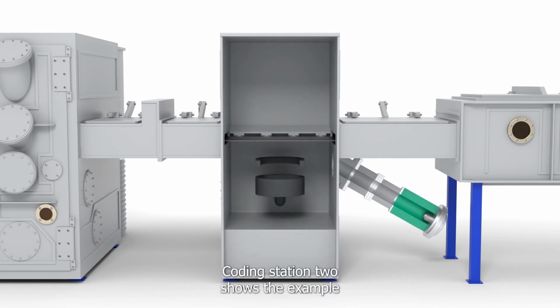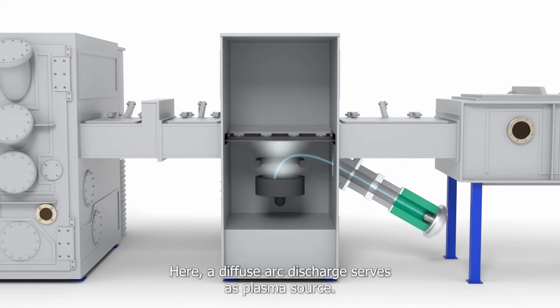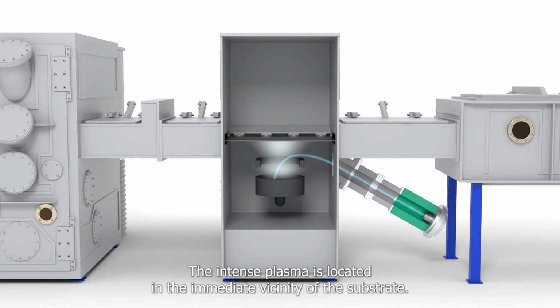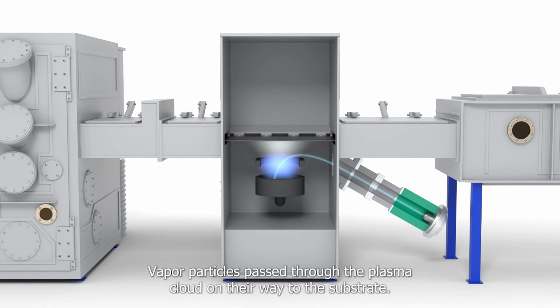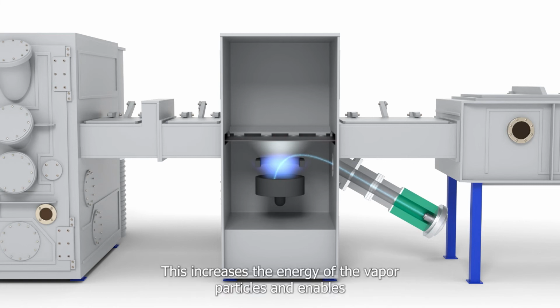Coating Station 2 shows the example of plasma-activated electron beam evaporation. Here, a diffuse arc discharge serves as plasma source. The intense plasma is located in the immediate vicinity of the substrate. Vapor particles pass through the plasma cloud on their way to the substrate. This increases the energy of the vapor particles and enables the deposition of particularly dense and smooth layers.